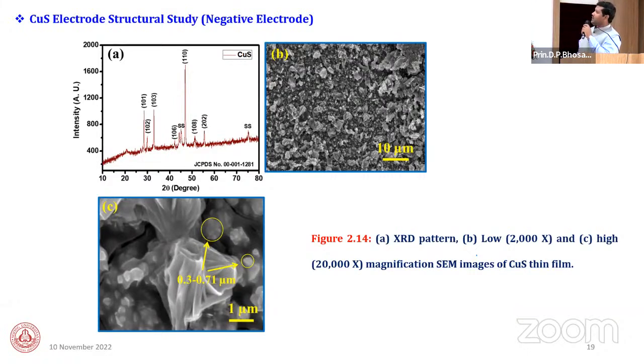So I prepared this CuS electrode using chemical bath deposition method, and I studied the electrochemical, structural and morphological properties. The XRD study confirms the prepared material is copper sulfide on a stainless steel substrate. Because of this, the stainless steel peaks are observed in this XRD pattern. In the morphology, microflowers with microparticles are observed on the surface of the stainless steel substrate. So the prepared material is used for the negative electrode as well.